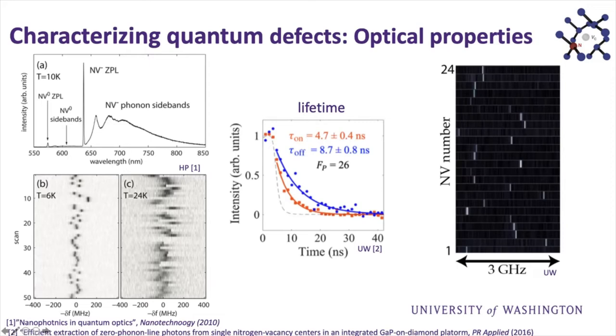We have ways as a community that we can stabilize this transition somewhat via certain optical excitation schemes, as well as feedback on that transition. If we just look at one line, what we need to know is that this line width, which is about 10 megahertz or so, is Fourier transform limited. So we need to do lifetime measurements on these, take the Fourier transform of it, and back out that we have a spectral width that's transform limited.